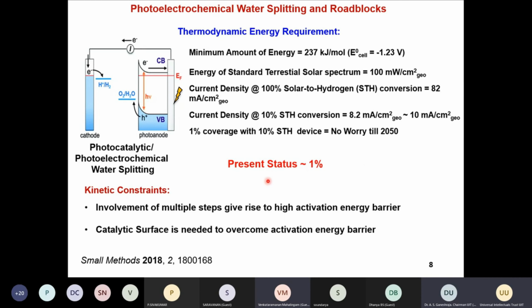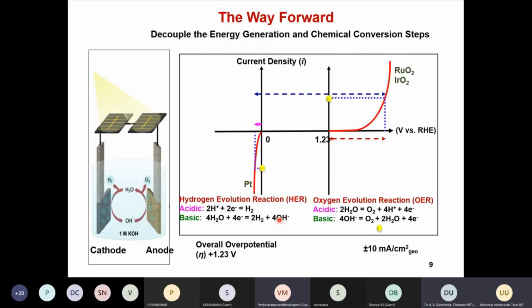So what is the major problem? The problem in getting hydrogen from water is the kinetic constraints. It involves multiple steps, which brings a high activation energy barrier, and the catalyst surface is needed to overcome this activation barrier. That is the reason we need a very good catalyst to produce hydrogen from water. In general, the best thing is to couple the solar light, the energy generation, and the chemical conversion, both steps. However, water splitting is a very complicated process. It has several activation barriers. That's why you have to decouple and work on both separately.